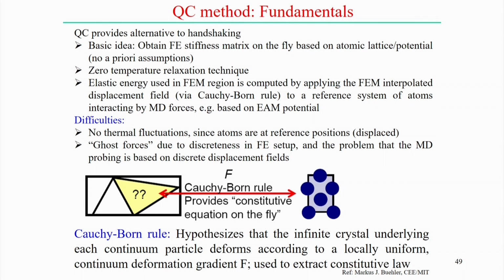Now, the quasi-continuum method actually provides an alternative to handshaking. The basic idea is to obtain the finite element stiffness matrix on the fly based on the atomic lattice or potential, not requiring any prior assumptions. In the zero temperature relaxation technique, the elastic energy used in the finite element region is computed by applying the finite element method interpolated displacement field, using the Cauchy-Born rule for example, to a reference system of atoms interacting by molecular dynamics forces based on the EAM potential. But the difficulty is that there is no thermal fluctuation since atoms are at reference positions. Therefore, sometimes there are ghost forces due to the discreteness of the atomic system, and the problem that the molecular dynamics probing is based on the discrete displacement field.